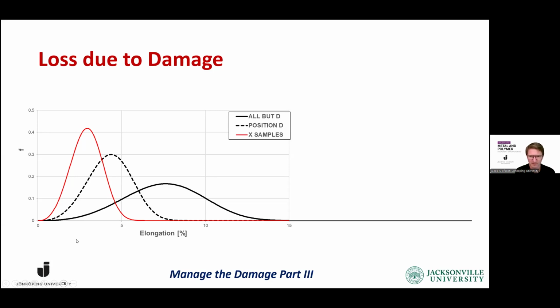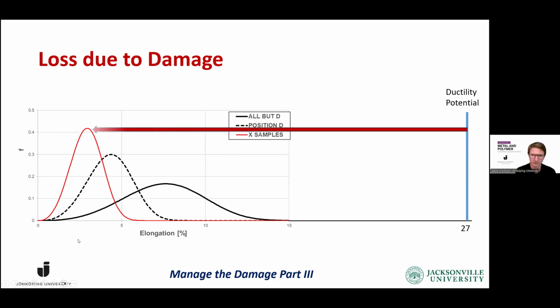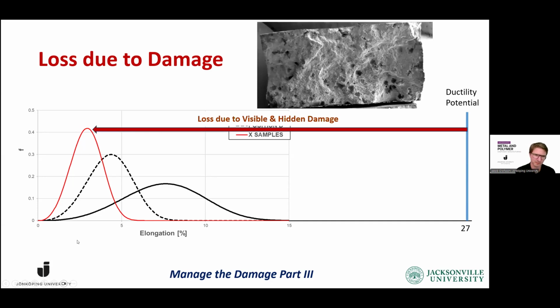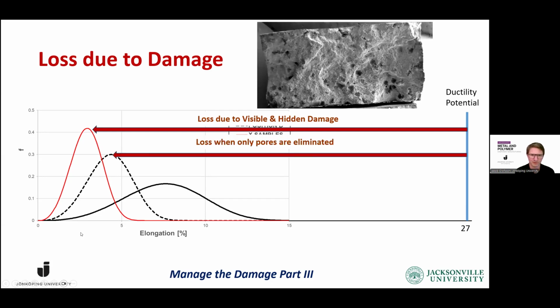And you remember I said that the ductility potential of this material was around 27%. So that's the potential that we should be able to reach. But due to the fact that we have visible and hidden damage, you see we are cutting away and removing quite a lot of elongation. We are only reaching about 3.5-4%.